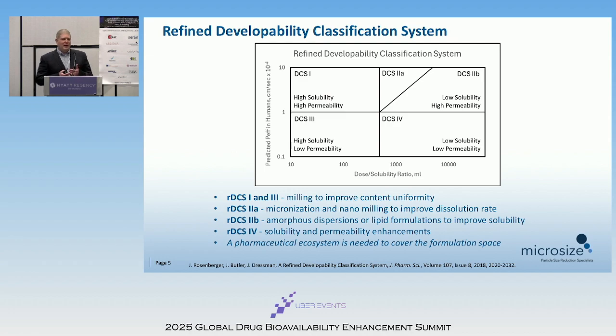I recommend for even DCS1 and class 3 compounds to add some form of milling. Not that you're trying to enhance the solubility or enhance the dissolution rates, but just overall it helps with content uniformity. I have some really cool SEM images later on that show what happens when you blend particles that do not have a size match.